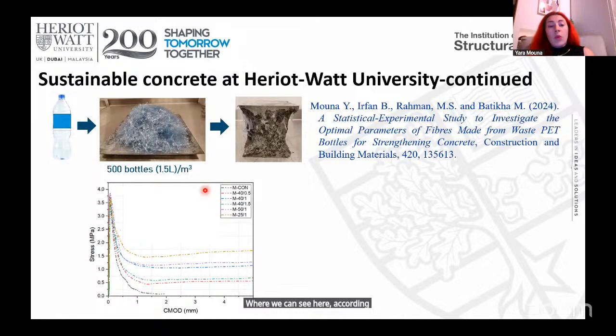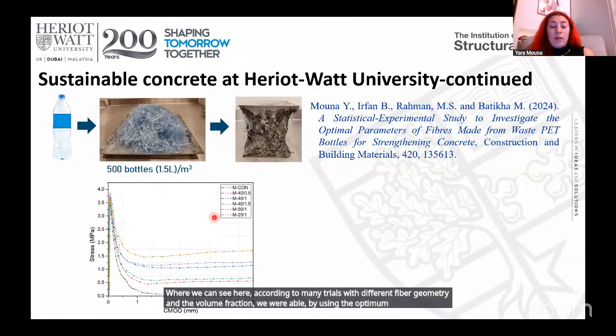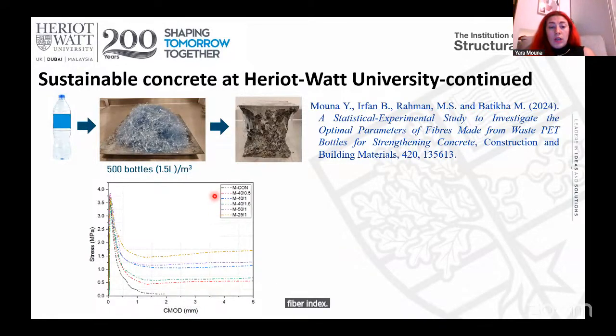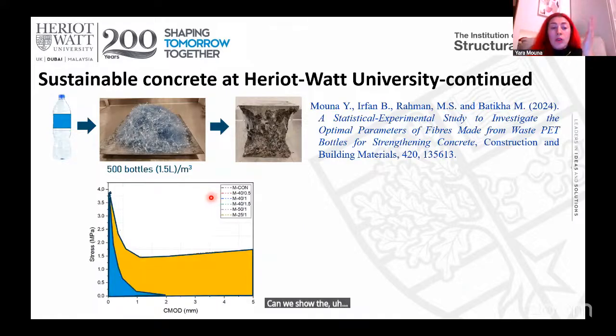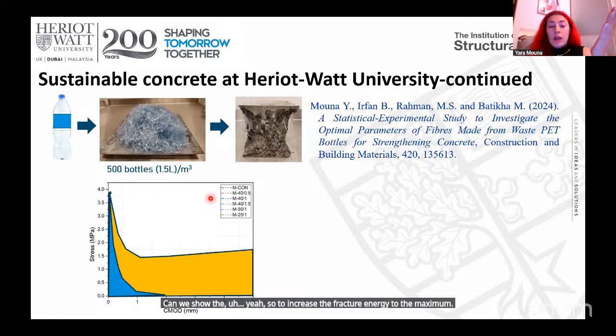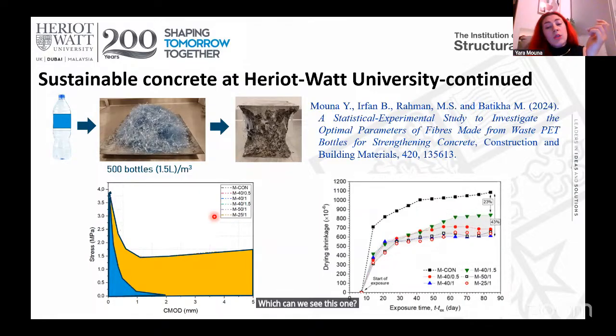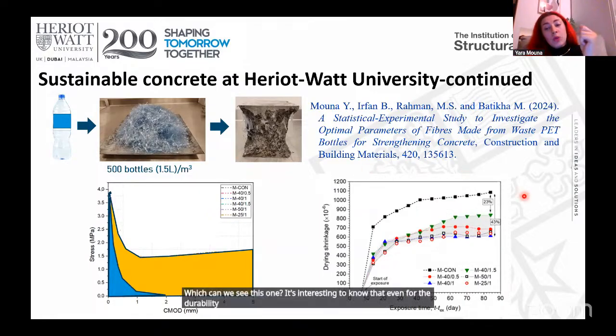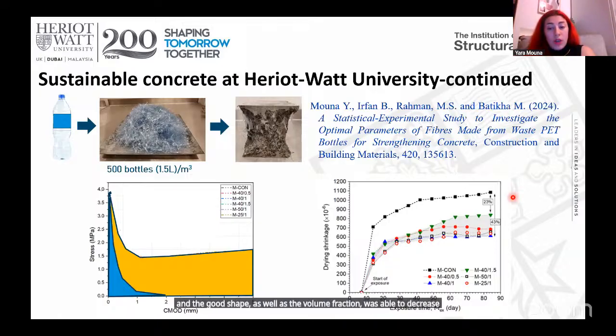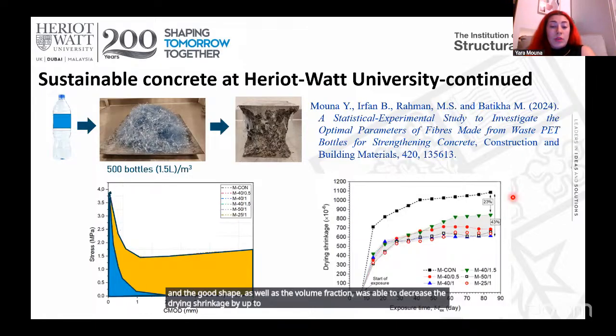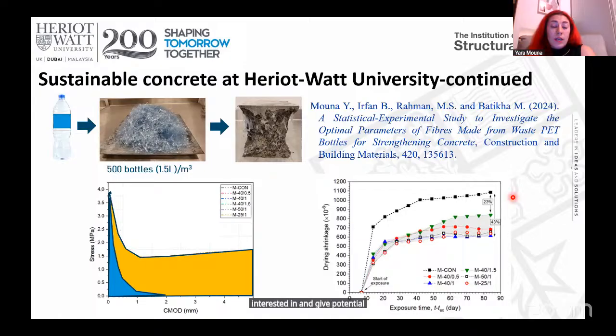The combination of them gives us the optimum quality of the fibers. According to many trials with different fiber geometry and volume fraction, by using the optimum fiber index, we were able to increase the fracture energy to the maximum, and this is reflected by the area under the stress-CMOD graph. It's interesting to know that even for the durability properties, the use of the optimum fiber index, which is a combination of the good geometry and the volume fraction, was able to decrease the drying shrinkage by up to 43%, which gives potential to this kind of mix.